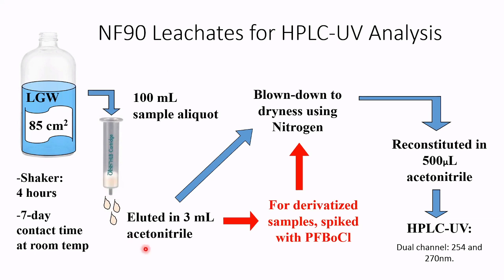Then we eluted that with acetonitrile, and in hopes of further concentrating, my sample went from 100 mL to 3 mL. In hopes of concentrating that even further, we can use something called a blowdown, which will evaporate extra solvent and hopefully retain your analytes in the sample. So then we blew that down to dryness, our 3 mils at that point. We blew it until the sample was gone. And then we reconstituted that in 500 microliters of acetonitrile, which we then analyzed. And you'll notice here in red that some samples were derivatized. That's something we'll talk about in the next slide, but derivatization is useful for tagging compounds.